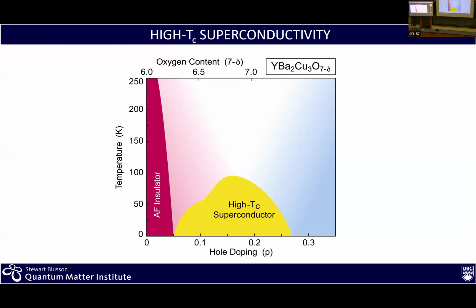Now, the next step was to go and look into not just the pairing symmetry, but also the phase diagram of this material. And this in itself is already very surprising. What you see here is a doping and a temperature axis. Doping means that you can change the number of carriers in this solid, in this particular case of yttrium barium copper oxide, by changing the amount of oxygen. It can be done after the growth. You grow your sample, and then by annealing at some condition in some atmosphere, you can change the oxygen content, and you move a number of carriers into this solid this way.